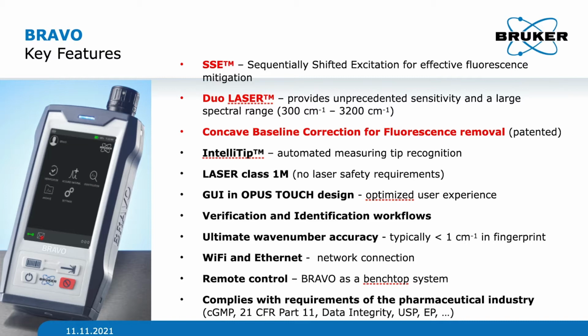And again, the graphical user interface known as the GUI is Opus Touch, the same as on our Alpha product, so you don't need to learn two different software interfaces. And again, you have the verification and identification workflows. Maybe most importantly, it has very, very high wavenumber accuracy, better than one wave number, and typically it's around 0.2 wave numbers. That's better than most lab systems that are out there. It's really important because remember, you're going to be searching databases for unknowns and databases again to verify. And the number one criterion used for those database searches is wavenumber position or peak position. So this is really important.